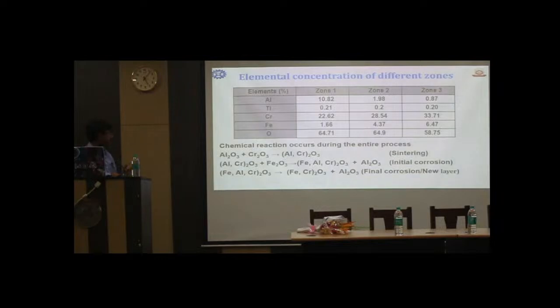So based on these things, we propose this may be the reaction mechanism, how the corrosion takes place. When you use alumina and Cr2O3, during the sintering process, it forms the alumina chrome solid solution. This is the first step. This reaction takes place during the sintering process.